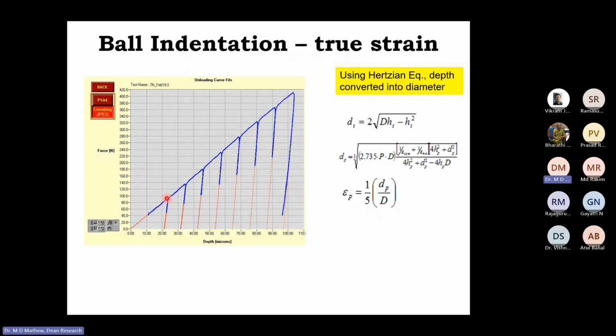So once you have this blue colored graph, which will be generated in a ball indentation test, you process this data, okay, you extrapolate it to the zero load so that you get what is called the permanent depth of penetration. That is what I call HT. And then capital D is the diameter of the indenter. So from that, you can determine what is the total diameter of the indentation. So from the depth, we are now getting the diameter value.